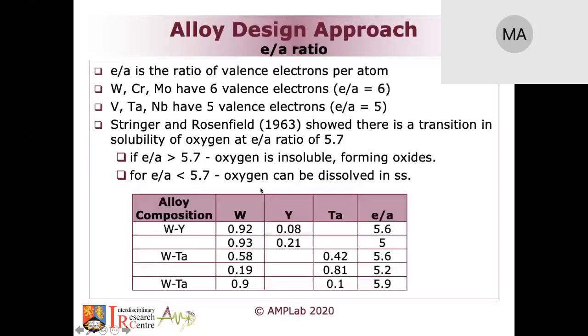Just for the sake of the exercise, if you have an alloy containing 92% tungsten and 8% yttrium, that is going to give you an E/A ratio of 5.6. So this is an alloy that is essentially not going to be susceptible to cracking, because oxygen can be dissolved in the solid solution. If you look into tungsten tantalum, for instance, at 58/42, that's 5.6. If you want a tantalum-rich alloy, that's 5.2. If you want a tungsten-rich tungsten tantalum alloy, that will raise it to 5.9.